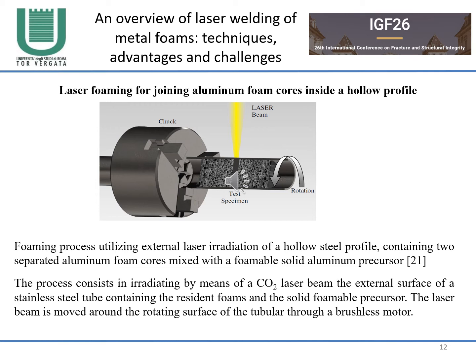The process consists in irradiating, by means of a CO2 laser beam, the external surface of a stainless steel tube containing the resident foams and the solid foamable precursor. The laser beam is moved around the rotating surface of the tubular through a brushless motor.